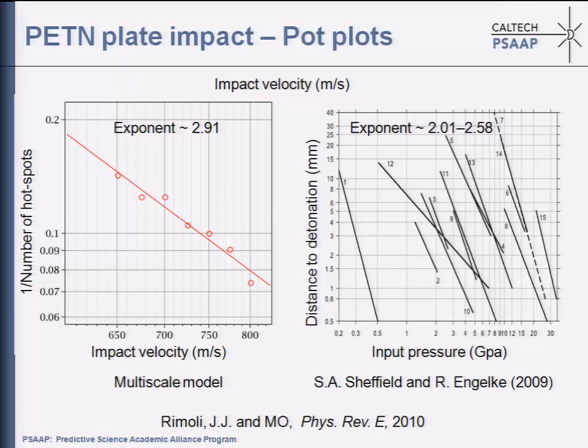Okay, so with the multiscale model, because we have control on hot spots, we can produce more or less the same plot and exhibit also power scaling of some type. So from the model that we use, we get an exponent, which is 2.9, whereas for PETN, you get exponents in the lab that are perhaps 2.5. So there's still a little bit of a gap.